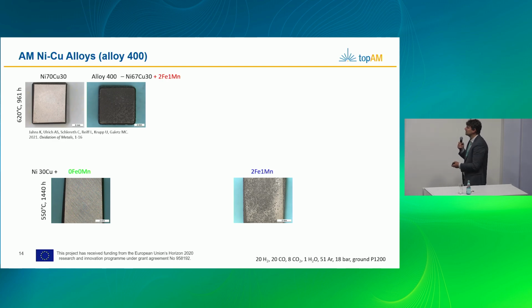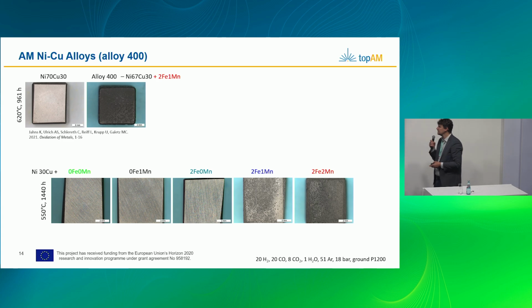So we tried, and here after 1,440 hours, same exposure basically, when you leave out the iron and the manganese, we don't have this type of attack. So a slight change, and this is something that we can also do way more easily with AM methods in the powder composition, can determine if we have the corrosive attack or not. So this gives us a nice way to really design the materials, and in this case it's even more funny, because when we have iron and manganese in it, the corrosion is pretty strong. As soon as we leave out one of the two components, the corrosion decreases immediately. So this is a good opportunity to design the powders and remove the manganese and the iron.